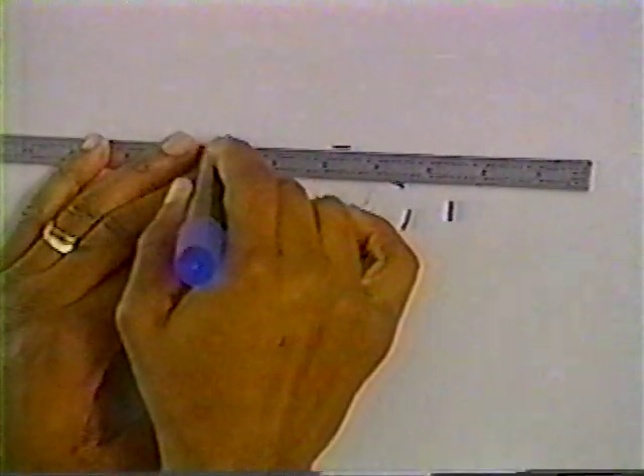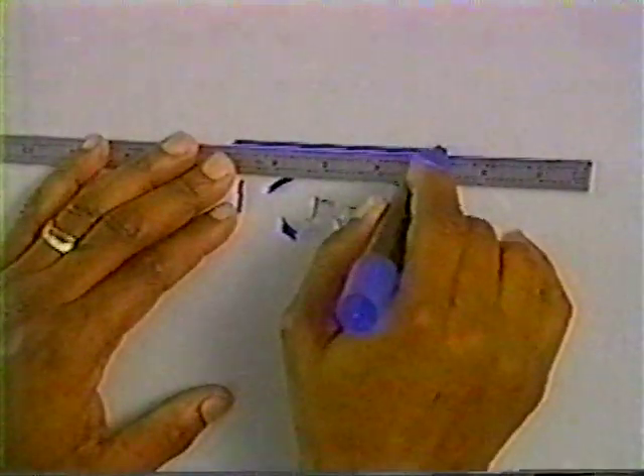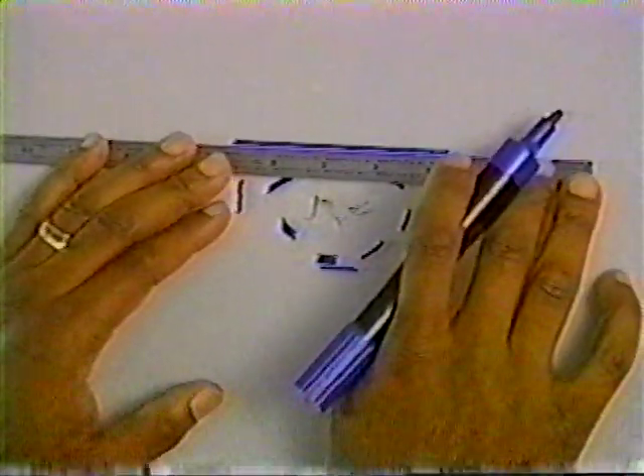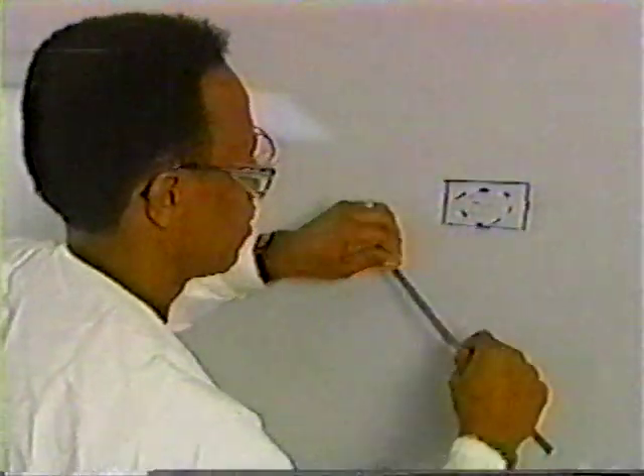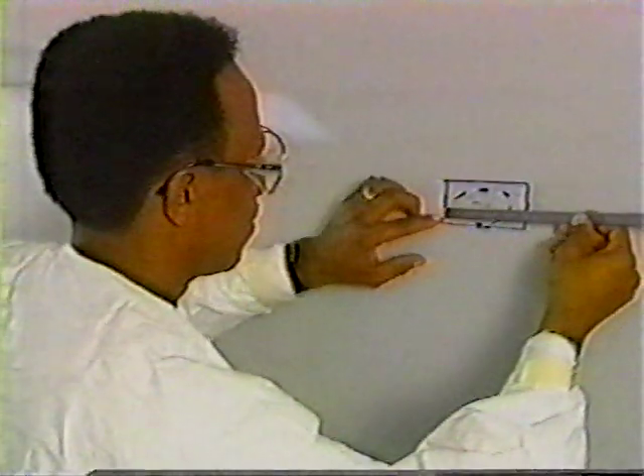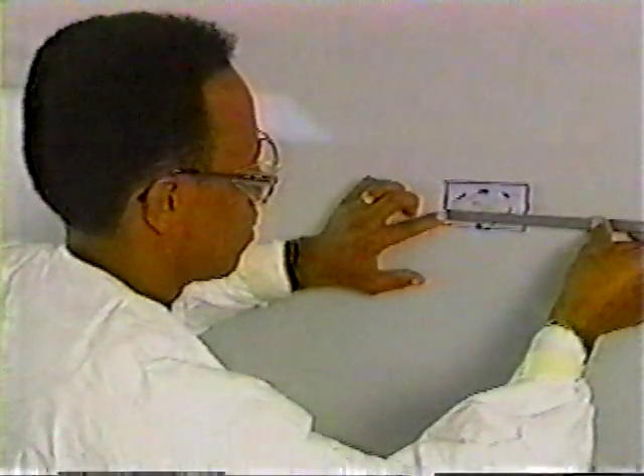To begin, lightly tap the panel around the damage site to determine the extent of the delaminated material. Once the area of delamination has been identified, mark that area on the panel. Then, measure these dimensions so that a template can be made, which will later be used to cut the fill plies.